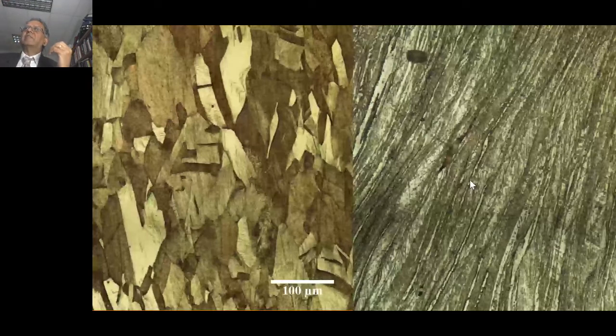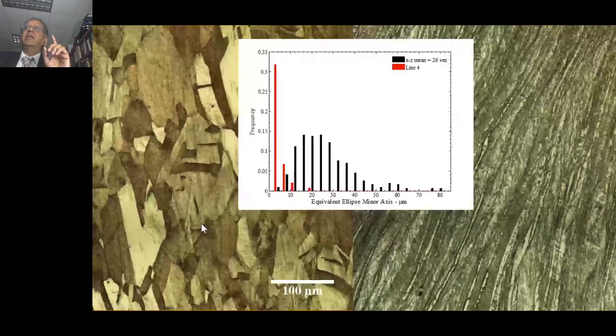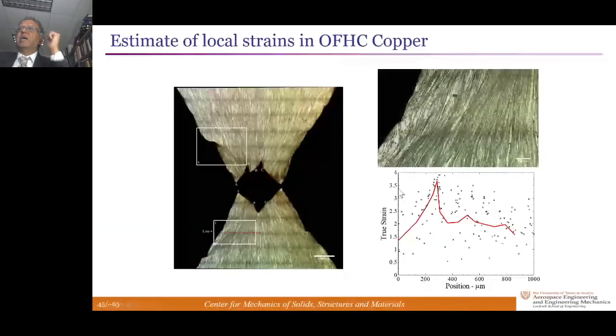So the strain levels here can be measured simply by looking at grain statistics before loading and grain statistics after loading on a point or a region-wide basis. And these strain levels are enormous. This is how you calculate the strain, but I'll go by that. Strain levels locally are on the order of 2 to 3 without any damage. This is pure copper, and it can go to such strain levels.